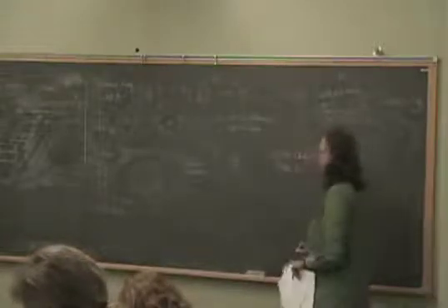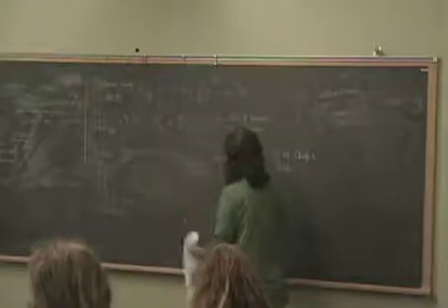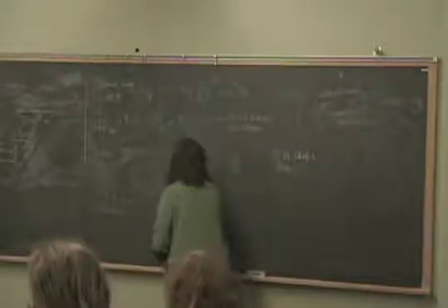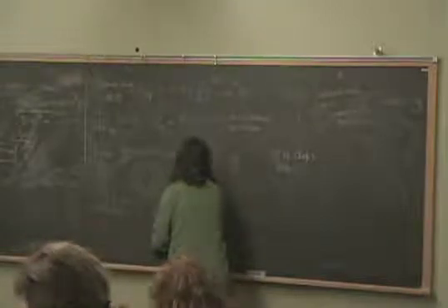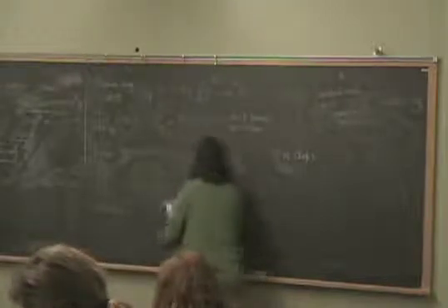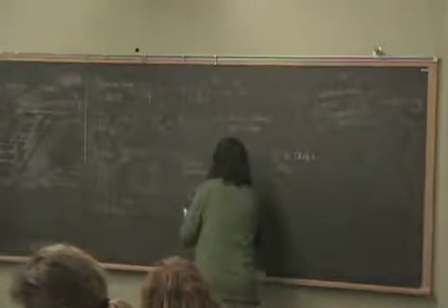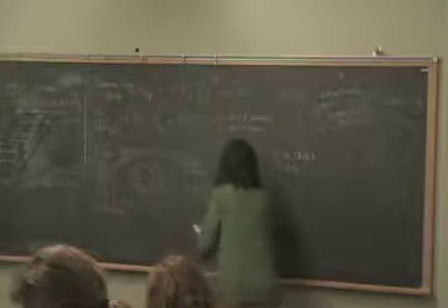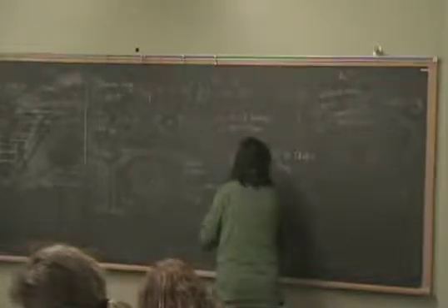So you get the square root of 3 for a sphere, and so the frequency is reduced, and that basically says that E surface plasmon for a gold sphere would be about 9 eV over square root of 3. That's 1.73, and that's about 5 eV.